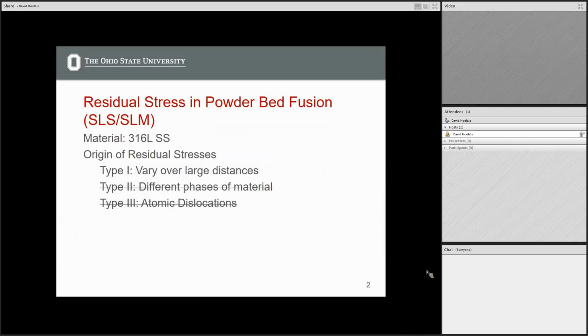So we're going to be taking a look at residual stresses in these powder bed fusion processes. The material that they were really focused on was 316L stainless steel, which is a common material, as we've seen in a lot of our classwork. However, they do go into a little bit about what will change if you begin to change material properties. And one of the main things they throw at you immediately in the paper is that they're only worried about type 1 residual stresses, which vary over very large distances. They're not as concerned with type 2 and type 3, which are different phases of the material, so liquid to solid, and those that arise through atomic dislocations. So we're going to be ignoring those and really focus on the process applying residual stress to the parts.